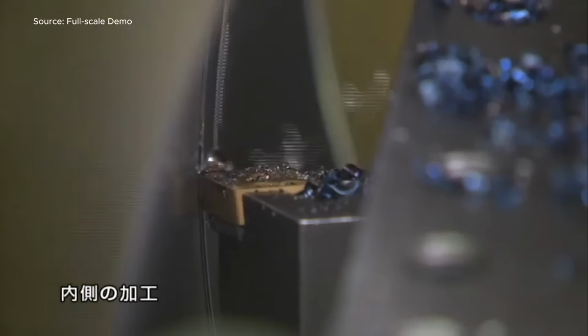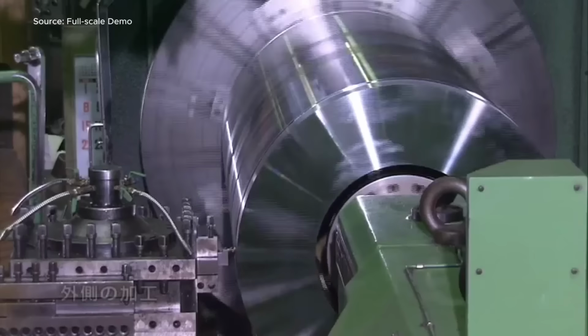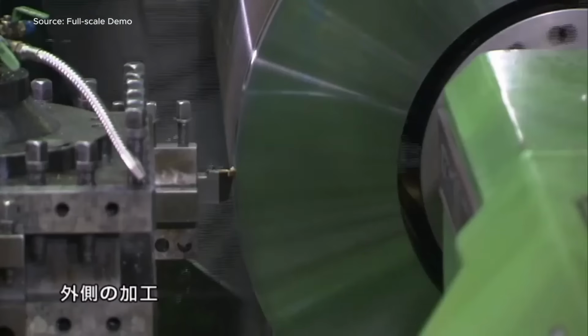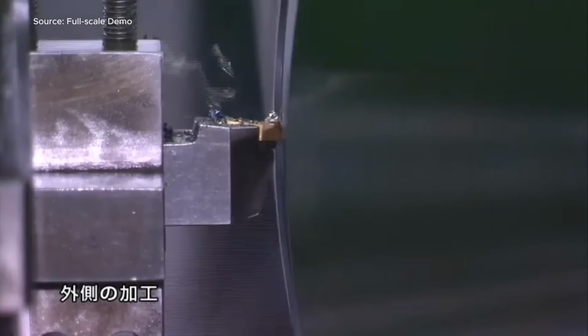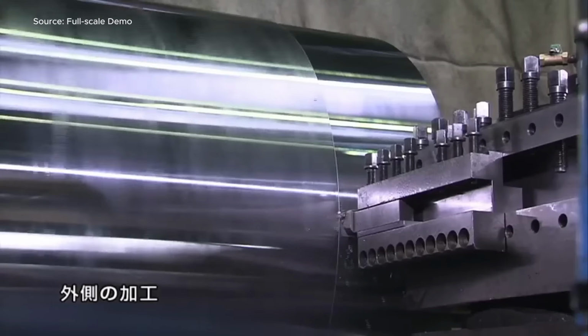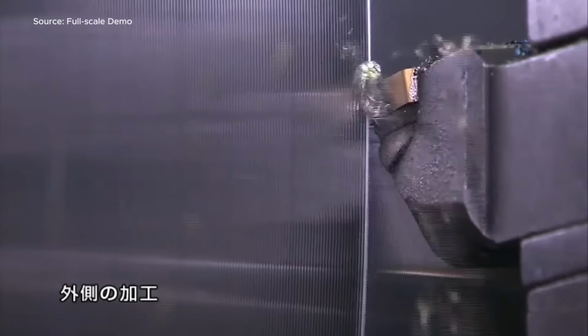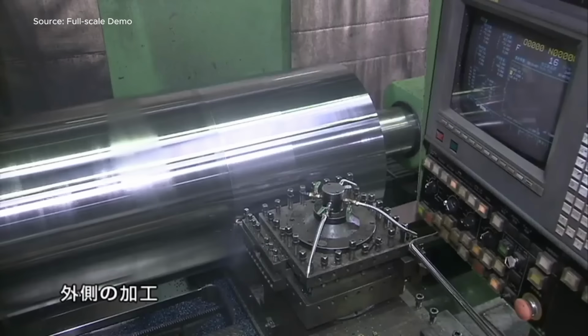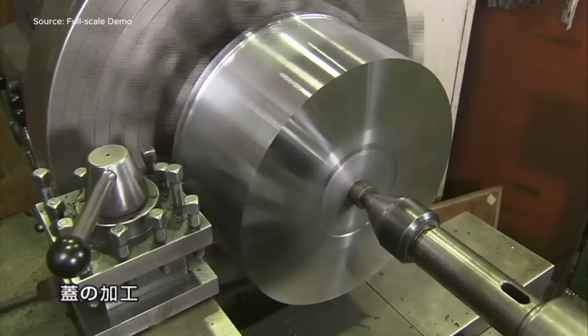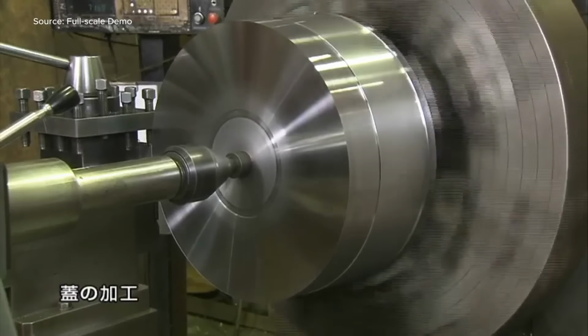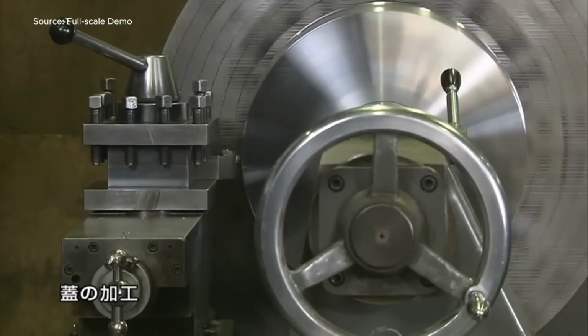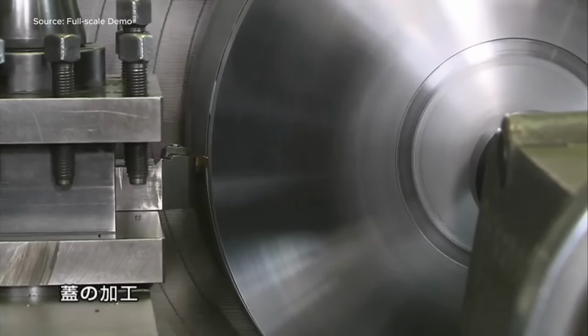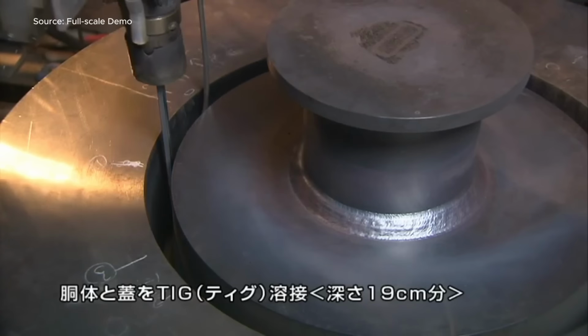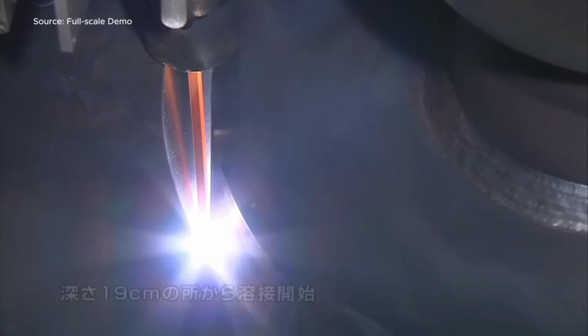When both parts are ready, they are joined together using TIG welding, a process that demands skill and concentration. The weld penetrates 19 centimeters deep, with the container rotated steadily at 6 to 10 centimeters per minute, ensuring even fusion at every point. Final welding is performed just 2 centimeters from the surface, sealing the overpack completely.